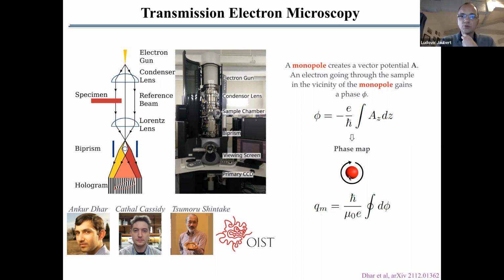So that's how, from this vector potential, you get the phase shift phi, and from the integration over a contour around a given point. If you don't have any magnetic charge, this integration will give you 0. But if you have a magnetic charge, this integration will give you a finite value corresponding to the magnetic charge Qm here.